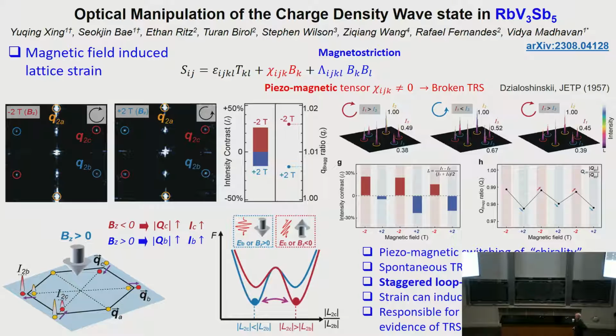So really, what is happening is the system breaks time reversal symmetry spontaneously. And using the piezomagnetic effect, if that breaks time reversal, this is non-zero. So you can use a field to probe this piezomagnetic effect, and that causes the chirality flipping. So spontaneous time reversal symmetry breaking. I have not put in, we can actually have a loop current pattern that is consistent with these observations.